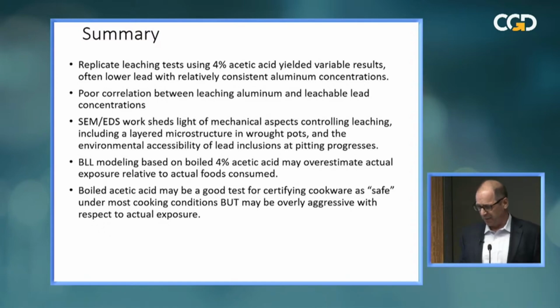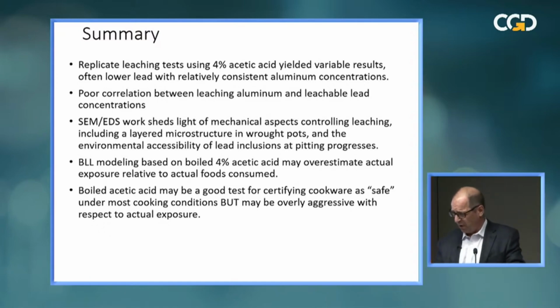Our replicate leaching was poor, but that's okay. And we also had poor correlation between how much aluminum versus how much lead leached. More leaching aluminum did not necessarily result in higher lead. Okay, and I think our SEM EDS work helped shed some light on the mechanical aspects of what's controlling the leaching and the environmental accessibility of lead.